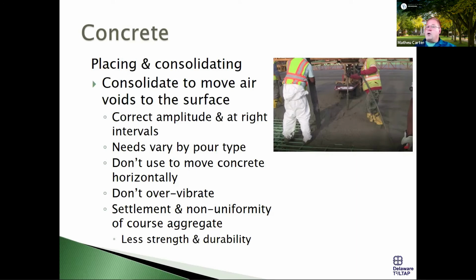Again, if you're working on internal concrete, you don't have that concern typically because you're not using air entrained concrete. But yeah, I think if you have a specification that is stronger in that regard, that's probably a good thing. I think the more you can encourage good behavior with the use, A, waiting until the bleed water comes off, and B, avoiding the use of steel tools, the better off you are.